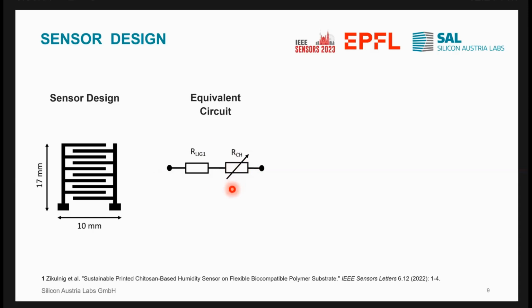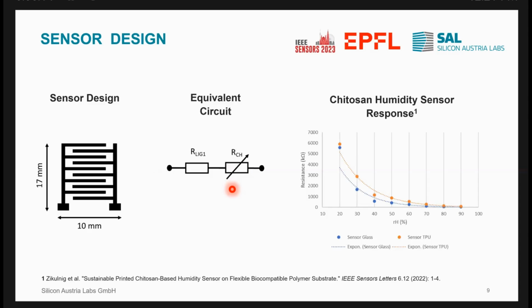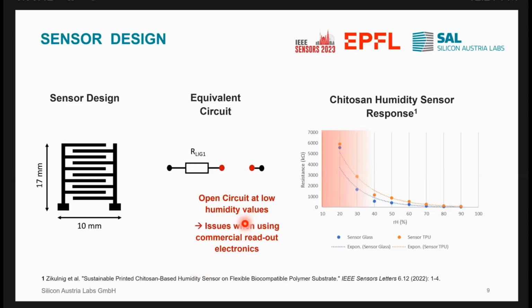that changes with the ambient humidity levels. In a former publication, we have shown this concept, but in this case not with LIG yet, but with inkjet printed electrodes, and it becomes obvious that at rather low humidity levels, the resistance of the LIG layer becomes very high. So at low humidity levels for commercial readout electronics, you can consider this more or less as open circuit at low humidity levels, which can pose issues when using this with commercial readout electronics or commercial sensing chips.